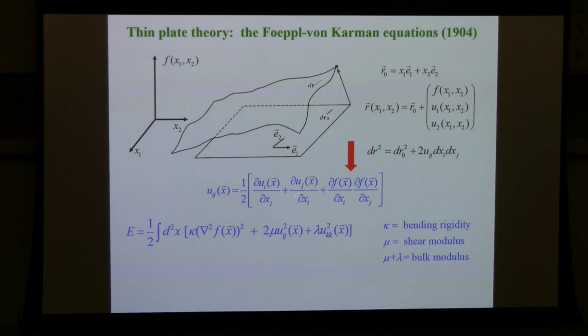There's this nonlinear term that comes into a strain matrix. This symmetrized strain is what you typically learn about in textbooks. And that's certainly true in 3 dimensions or in a rigid material in 2 dimensions that's on a substrate or something. But in general, there's this extra term that couples the out-of-plane flexural phonons to the in-plane strain. And some of you, if you know for example, the London theory of superconductivity, or the Ginzburg-Landau theory of superconductivity, this looks like a vector potential.